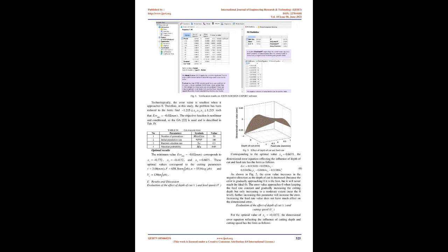The regression equation is rewritten according to the cutting parameters as follows: y equals 0.02365 plus 0.02961 (t minus t0)/Δt and 0.01234 (n minus n0)/Δn, minus 0.01845 tf terms, minus 0.01521 fn terms, minus 0.01989 f squared term, where t0 equals 6, Δt equals 3, f0 equals 700, Δf equals 100, n0 equals 4800, Δn equals 800, and limited values 2.247 ≤ t ≤ 9.753 mm, 575 ≤ f ≤ 825 mm/min, 3800 ≤ n ≤ 5800 rev/min.